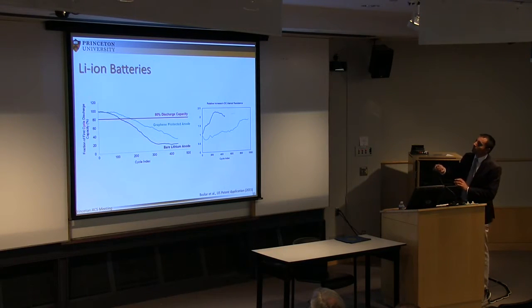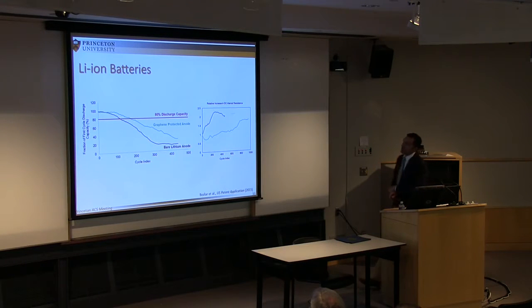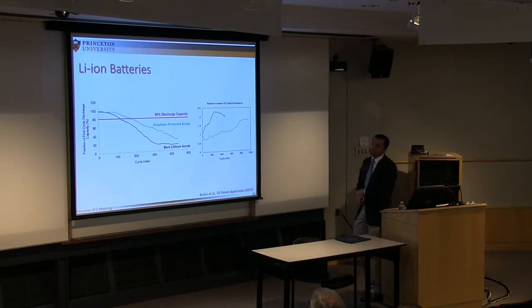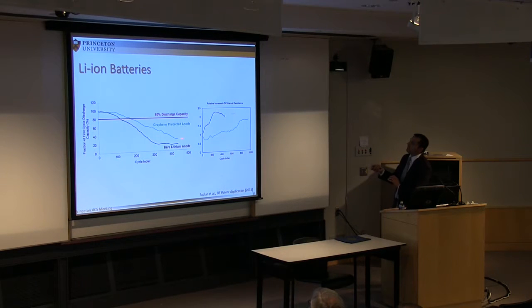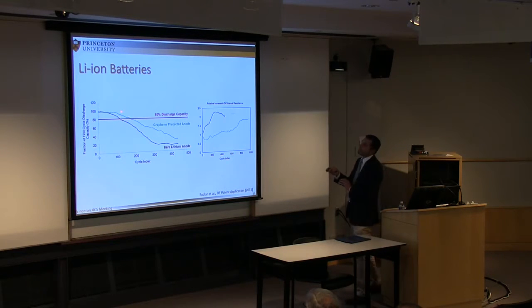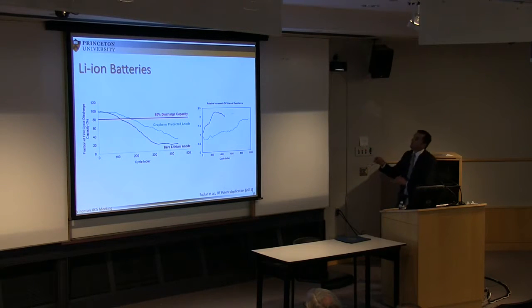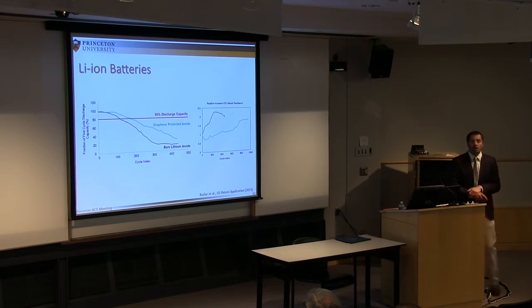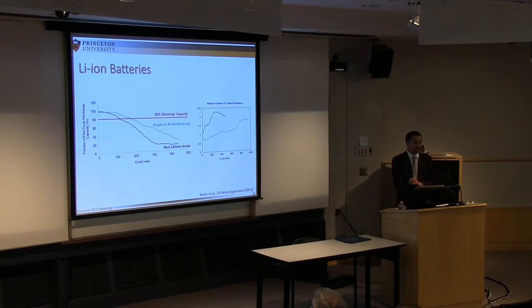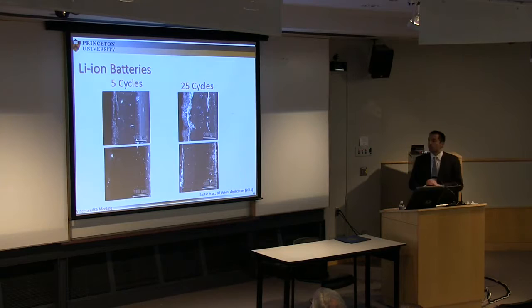If you look now at the discharge capacity, taking into account the first cycle as the basis, you see that when you have a bare lithium anode, the discharge capacity goes to less than 80% after 100 cycles, whereas if you use a graphene protected anode, it gives you about 25% or so increase in lifetime, which isn't bad. Together with that, the resistance increase, shown on the right, is minimized when you have graphene.